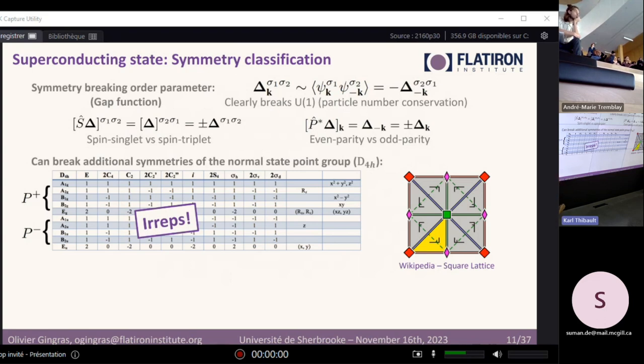So it's very, very easy for the system to respect the normal point group symmetries. But in unconventional superconductivity, it's thought to be repulsive interactions which force the gap to have these complicated momentum dependences, which leads to breaking of symmetries. So the way to discuss the breaking of symmetries is in terms of irreducible representations.